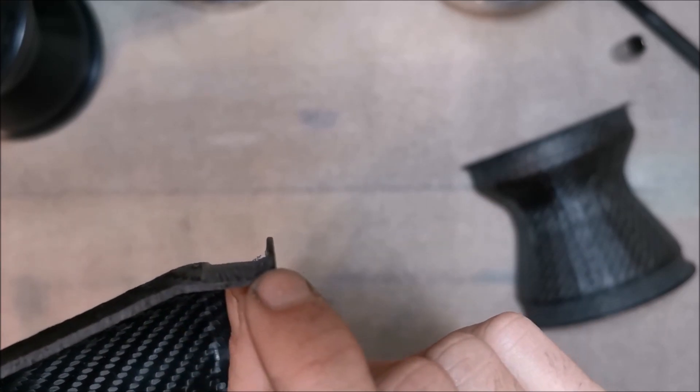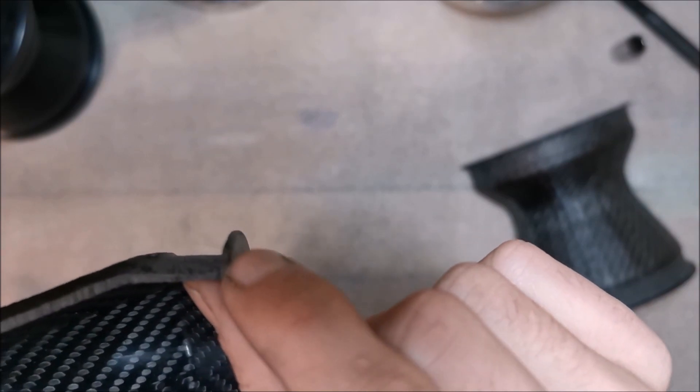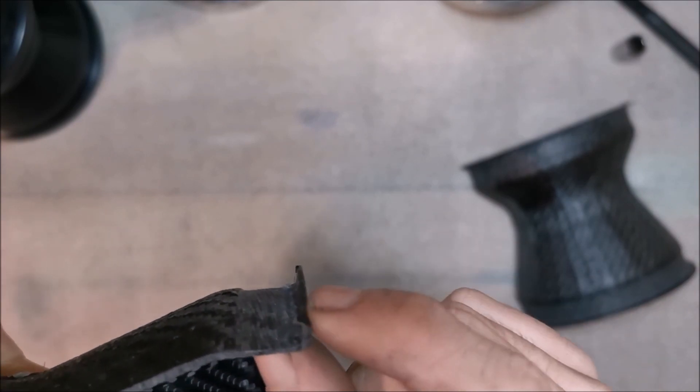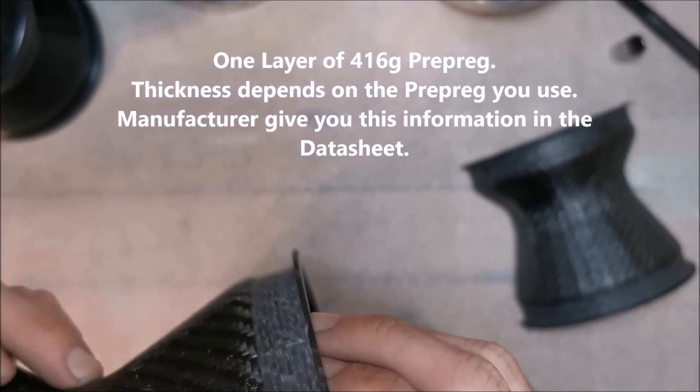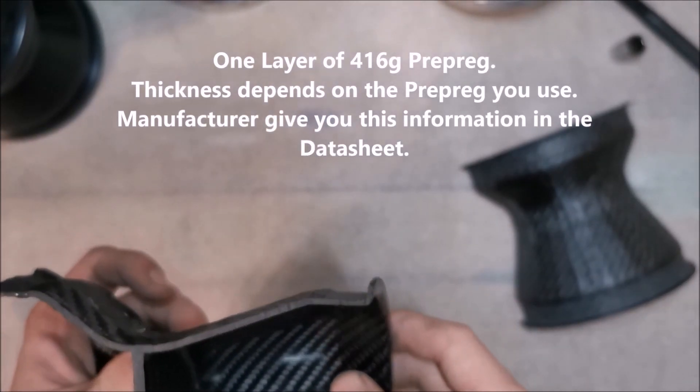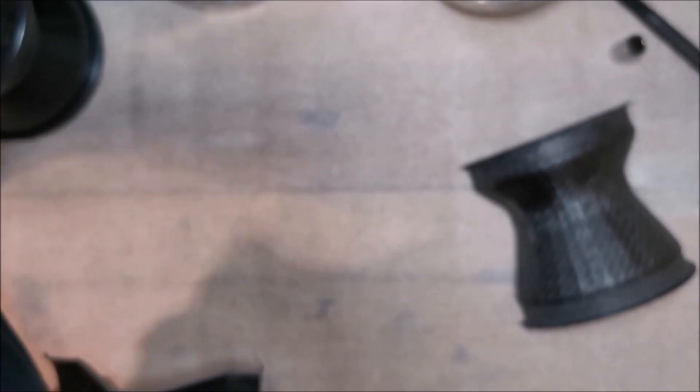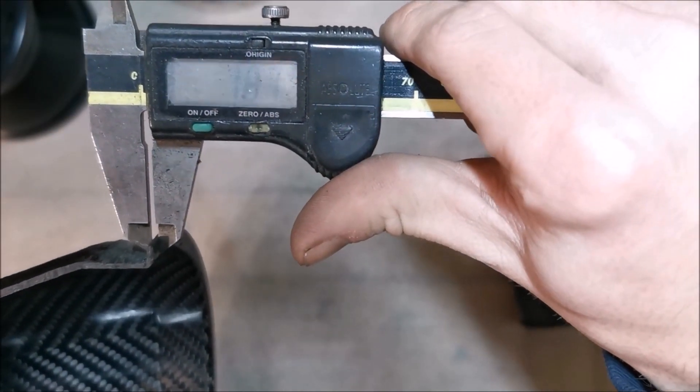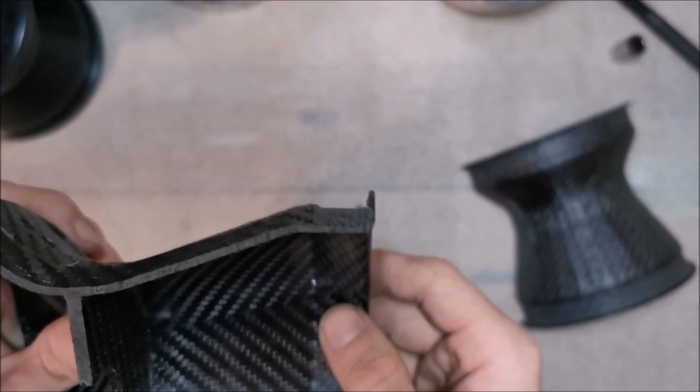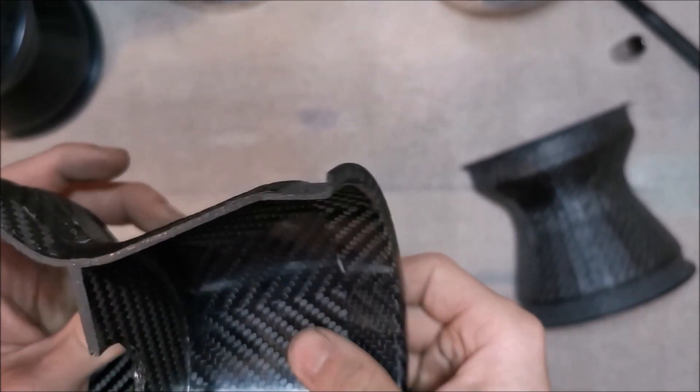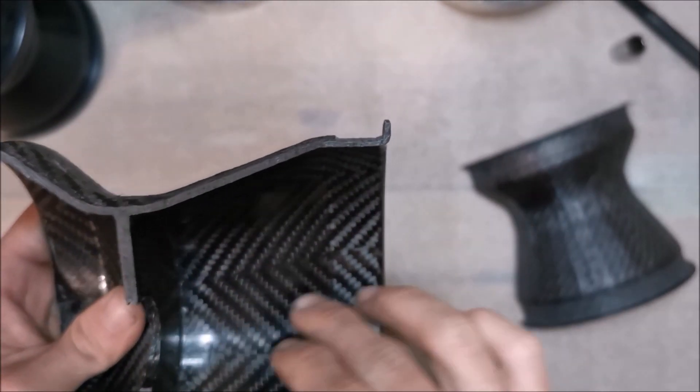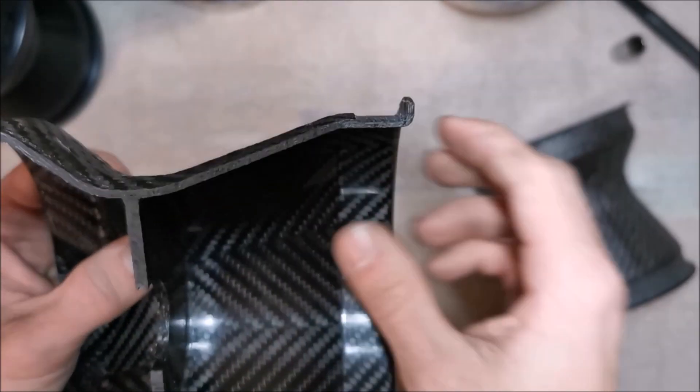But where I have to make some differences is here on the outer side. It's just small. Especially here where the tire presses against the rim. I have to make it a bit more thicker. One or two layers. The one layer is approximately 0.45mm. But this currently has 1.86mm. This is just too thin. And over this, from here to here, it is a straight. And a straight is never that good. And the longer it is, the more it tends to bend over here.